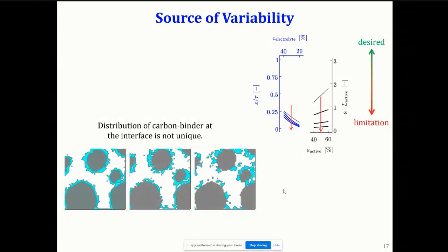The second source of variability is that we are not completely adapted to imaging these phases. We can see them in SEM or XRD, but what we really want to look at is the 3D distribution of things. And there we run into two methods. We either do FIB-SEM, which can detect all the relevant phases, but it doesn't give a large enough volume to make predictions at the electrode scale. And if you do tomography, you wouldn't be able to get the relevant contrast to image this material.